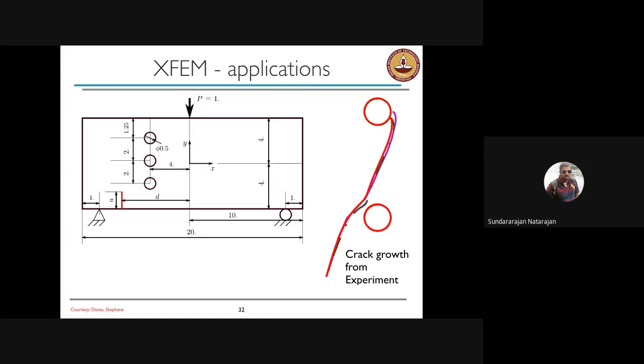Right, so we have applied this to many benchmark problems. One of the standard or classical problems is an experimental test case where you have a 3-point bend specimen with three holes, and there is a crack of length A, which is at a distance of D from the center line where the load is applied. Depending on the distance D, the crack would either go into the first hole, the bottommost hole, or it would bypass the first hole, go and merge into the second hole. And this is computationally very challenging to capture because you need an extremely refined mesh if I'm using a finite element method to do it.